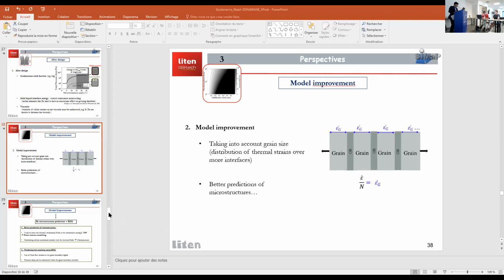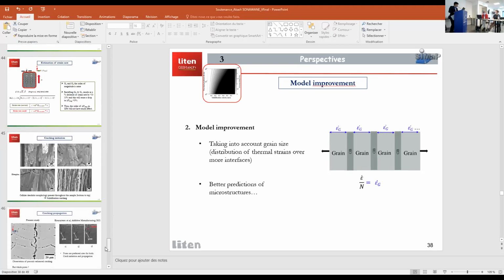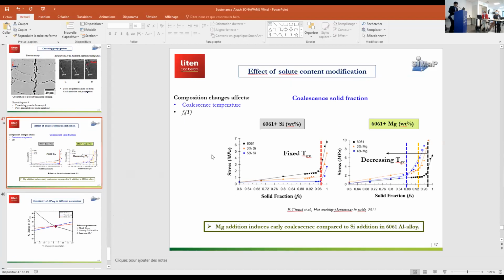No, in fact, what we think, it is true that coalescence is a transition aspect, but to my understanding, in order to detect coalescence, it's very tricky. But the experiments performed by Ilian Giroux were quite interesting, and I felt that it is the first time I found experiments done to detect coalescence. And they found that this coalescence is not in an arbitrary range. At a particular solid fraction, they clearly see that the stresses are increasing and the mushy zone is becoming much more resistant. And that is the first indication for me that coalescence is taking place at a constant solid fraction. In theory, but in practice, it occurs from the coherency point.